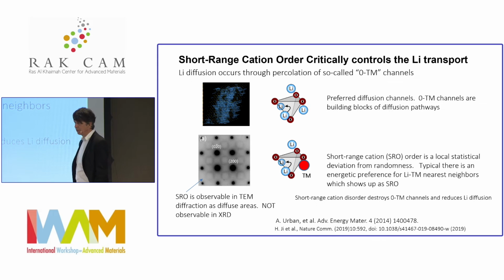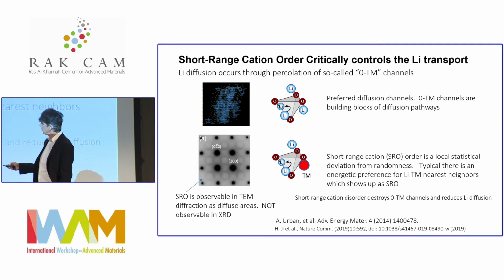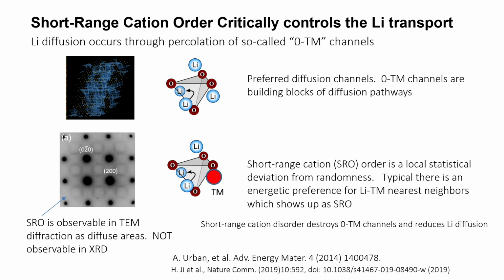And you actually see that when you do electron diffraction. So you see the typical Bragg peaks, and then you see this diffuse scattering, which is very pronounced, which is an indication of short-range order. And I'll show you it is extremely destructive to the performance.